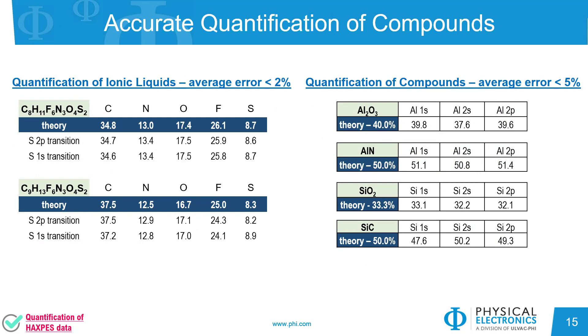The experimental sensitivity factors have shown good quantification results on compounds, as shown here. For these sulfur-, aluminum-, and silicon-containing compounds, good agreement to theory has been found using the traditional 2s and 2p transitions, as well as the newly accessible 1s transition.